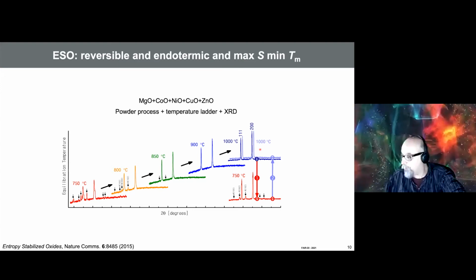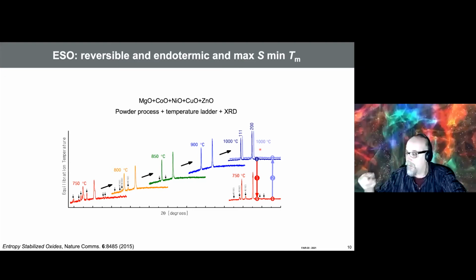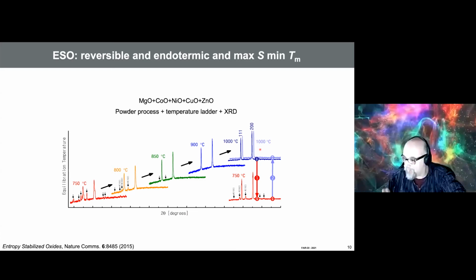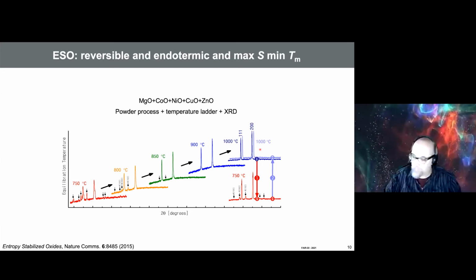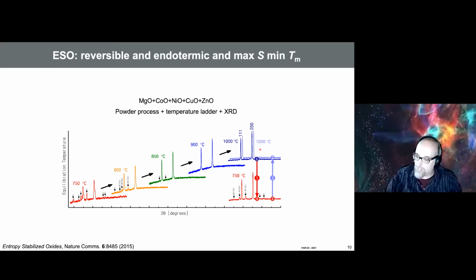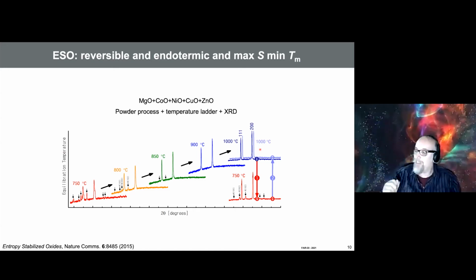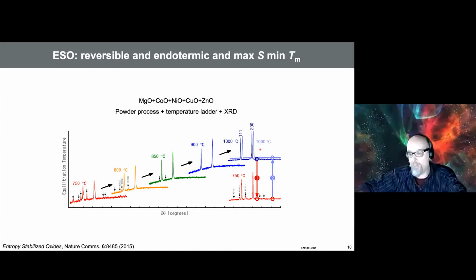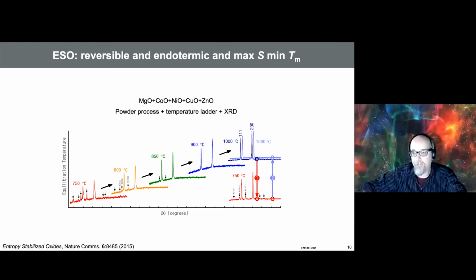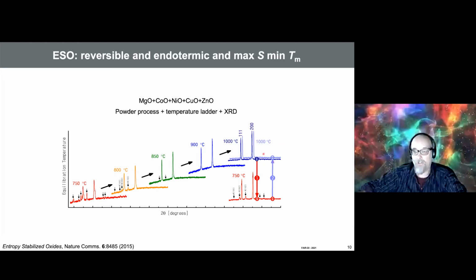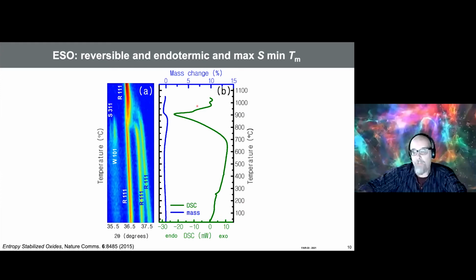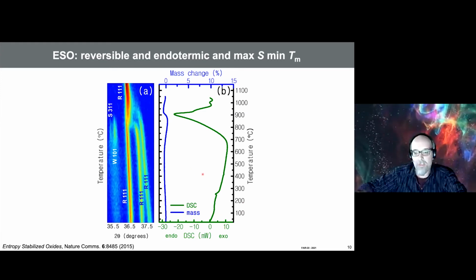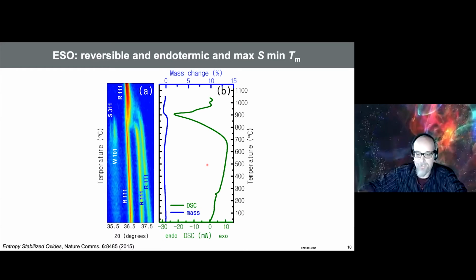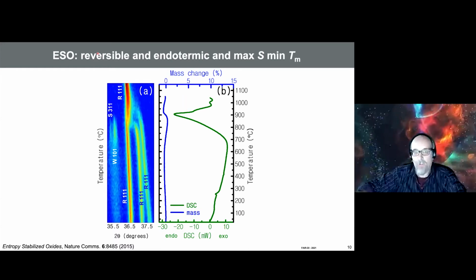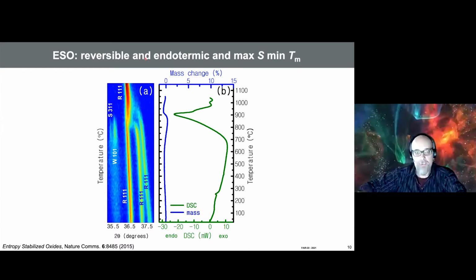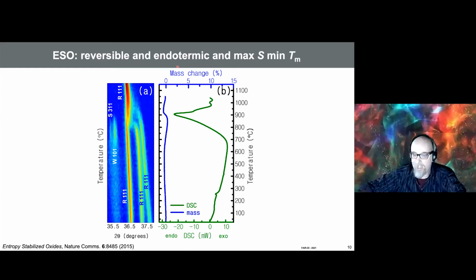Okay, which is very important, because every time you have a transition which is entropy driven, the change of entropy times the transition temperature is a latent heat, which we can use in a heat pump. I will show you later an example, right? Okay, so this is reversible. Then we checked it with differential scanning calorimetry, but that's not important. So more proof that it was an entropy transition, so it was reversible and endothermic, etc.